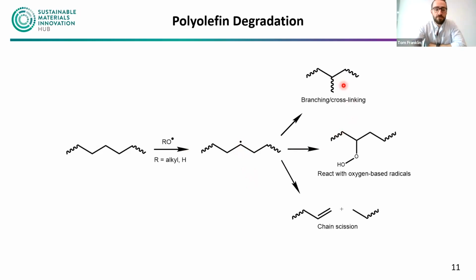So we get all these different types of reactions, again, all of which change our chemical structure and our physical properties, whether that be through the branching and the chain scission, as we've discussed, but they can also react to make other oxygen species, so a peroxide in this case, which in itself is quite reactive, and so you can get further complex reactions on top of this radical behavior. So it's quite a mix of different factors and different reactions taking place, but what we really want to do is stop this stage. We don't want these radicals to generate and to start these degradation reactions.